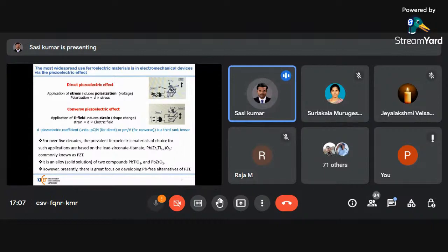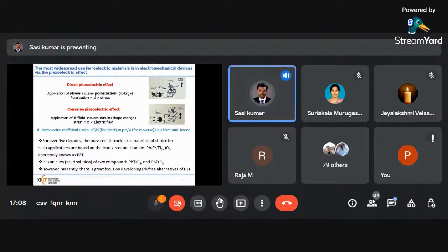The converse piezoelectric effect is when you apply an electric field to the material, which induces strain in the material. It is a shape change, which will produce some vibrations as output. So strain is equal to d times electric field. The d is the piezoelectric coefficient. Its unit is picocoulomb per Newton for the direct piezoelectric effect and picometer per volt for the converse piezoelectric effect. The piezoelectric coefficient is d33, a third rank tensor property.